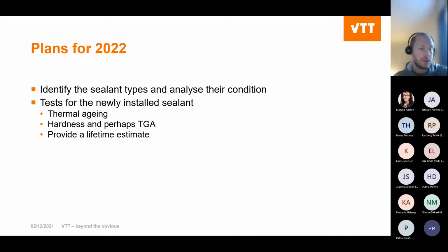And then we also have information about the newly installed sealant, which replaced these removed ones. It was a polyurethane-based Sikaflex sealant. So we are planning to do a small test matrix also with that material. Perhaps perform thermal aging and provide hardness and TGA. And then based on these results from the thermal aging, we could try to provide an estimate on the lifetime of this type of sealants, how long it would endure in plant use.